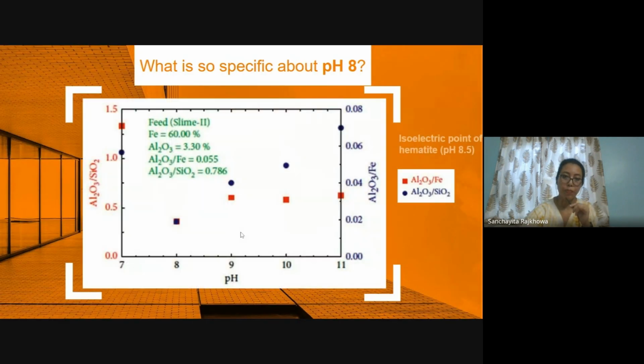Now, as I told, what is so specific about pH 8? If we consider pH 8, then a better quality of concentrate, that is iron more than 60%, can be obtained at pH 8. And moreover, the isoelectric point of hematite is around pH 8.5. That is one reason.